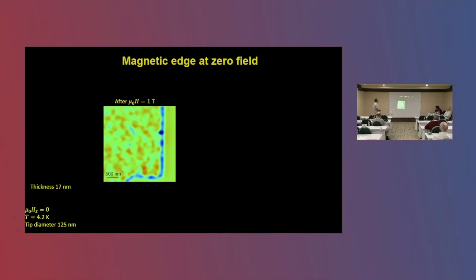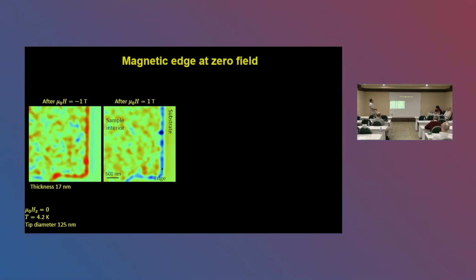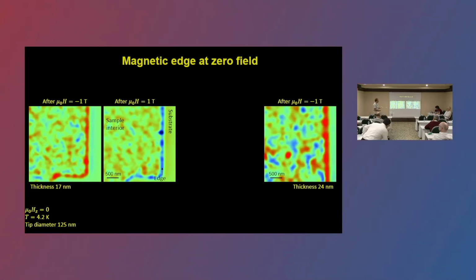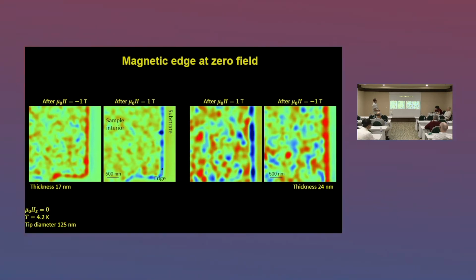And after looking for a while, we saw that actually the edges of the sample remain magnetized. So this is the sample, this is the sample interior, this is the substrate. This is the edge after an excursion at +1 Tesla at 0 field. And this is the same area of the sample at -1 Tesla. And you see that the edge stayed magnetized but reverted the orientation. We tried this on a slightly thicker film, and we also see this effect.